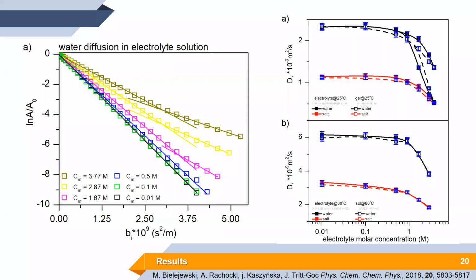So for low concentration, there is actually no dependence of the diffusion coefficient. This is because the ions are very well dissolved and far from each other. So basically, they don't interact, and they introduce no change in the composition, the density, or the viscosity of the electrolyte solution. However, when we go to much higher concentrations, we start to observe that the diffusion coefficient gets smaller. And this is something we can understand as the electrolyte solution becoming more dense and more viscous. So at some point, especially for high concentration, we observe biexponential behavior. The question was whether we have two distinct diffusion coefficients or a distribution of diffusion coefficients.